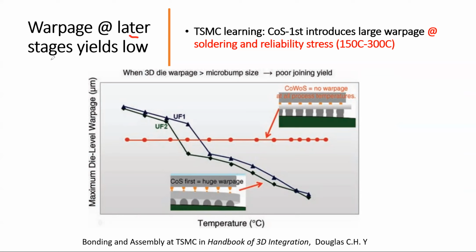But at a later stage, when you're heating up, when you solder them together, the temperature induces thermal stresses, or from the reliability stress test here. The temperature we're talking about is 150 to 300. That is enough to cause a huge warpage because these two layers have similar thickness. I'll explain that later. So this is one of the problems I'd like to show you here, about the wafer warpage.